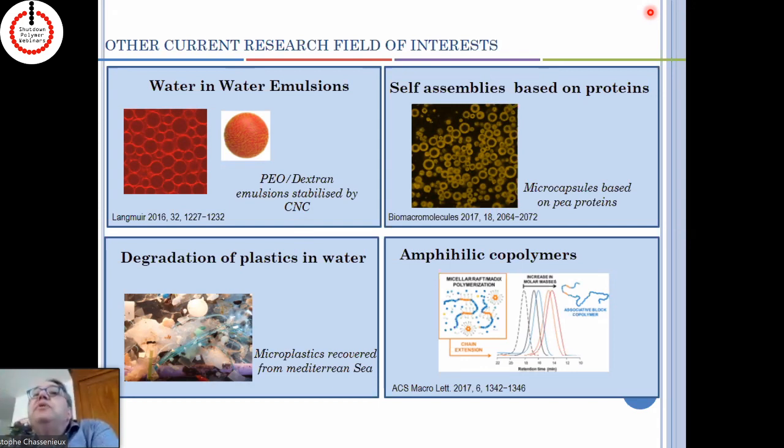The thing is that we have performed rheology with physically labeled polymer in order to see if it was important on the relaxation time. And since we keep this labeling amount pretty low, we measure exactly the same thing with or without rhodamine. Okay. Looks clear also for me.